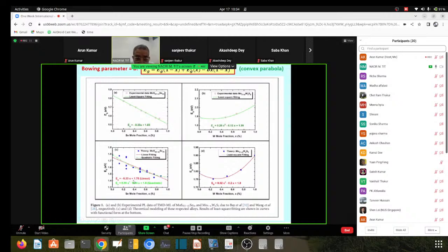Anyway, here you can see that we did linear fitting in the case of common cation, and we did parabolic fitting. We started with parabolic, which still looks more linear, but I meant it to be linear to compare with the experiment. So we found the law of bowing, written in red. I remind my students that the energy gap should vary as the energy gap of material A times 1 minus x, plus the energy gap of material B times x, minus b times x times 1 minus x.